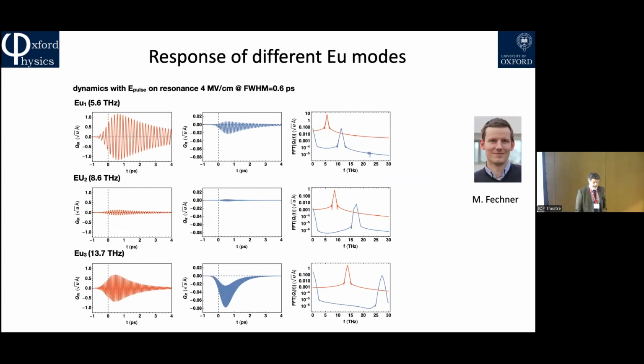What you can actually do in this case is carry out essentially a frozen phonon calculation by DFT, whereby you displace this Eu mode, and there are three Eu modes that are being considered, and the blue one is the response. As the question indicated before, you see there's a highly oscillatory component, but it's also a rectifier. Both are. And the hypothesis, we'll talk about this a bit later, is that this oscillatory component is what produces the displacement along the Raman coordinate that ultimately couples to the magnetic moment.